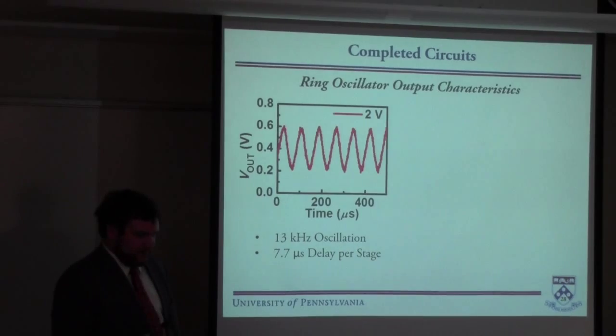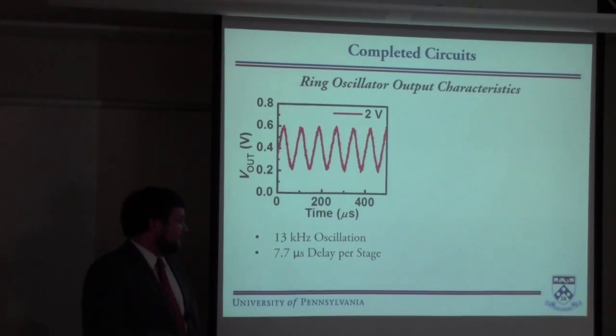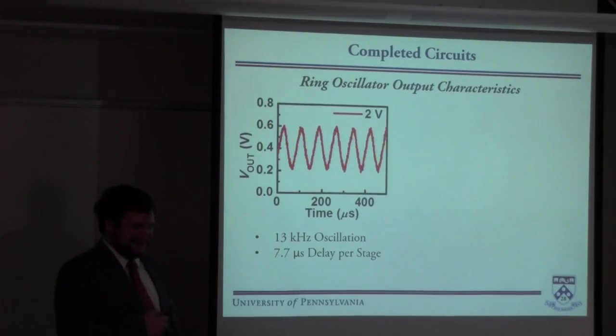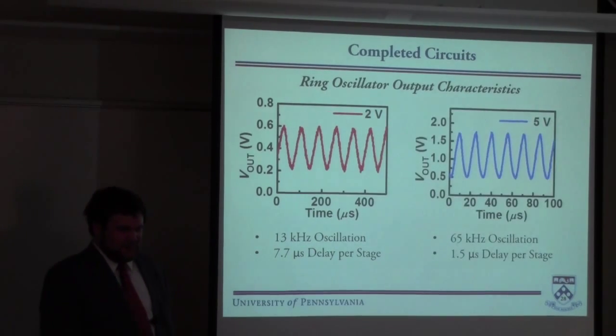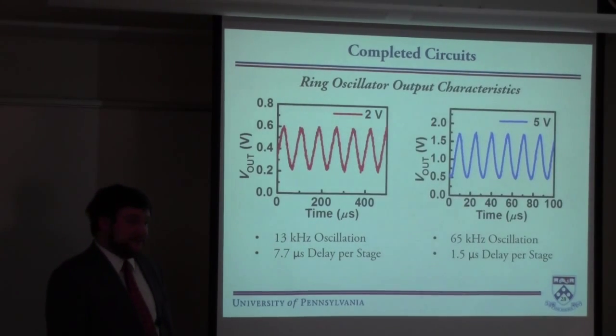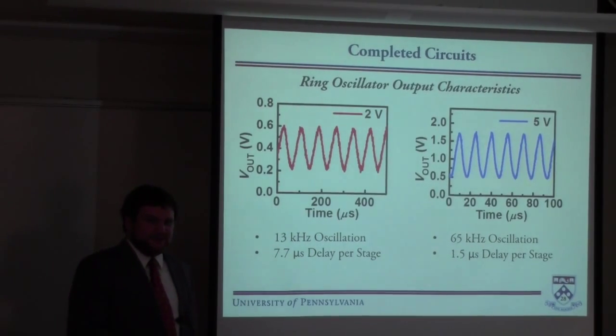So for our systems, at a 2-volt input, we got a 13 kilohertz oscillation, which is a 7.7 microsecond delay per stage. And at 5 volts, we got 65 kilohertz oscillation, which we were really surprised about, and a 1.5 microsecond delay per stage. We were disappointed we didn't quite get into the nanosecond range, but so close.